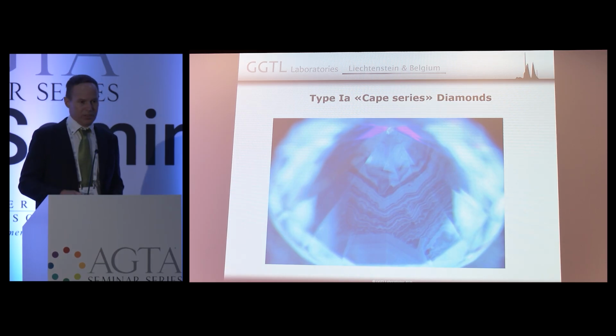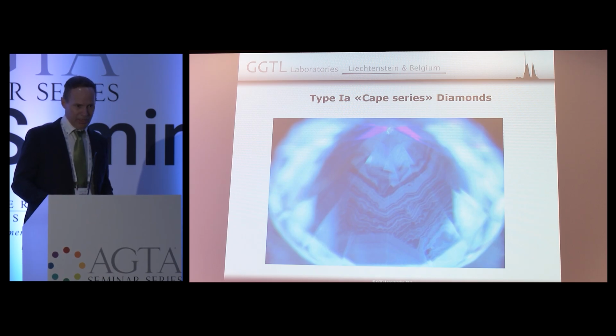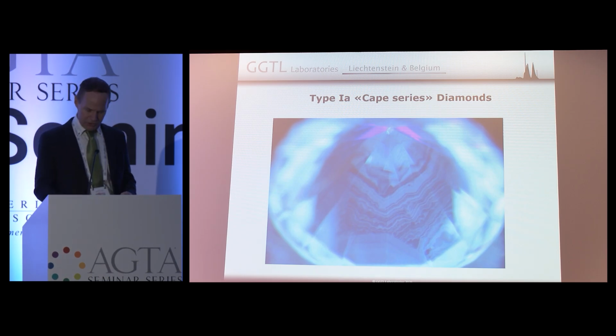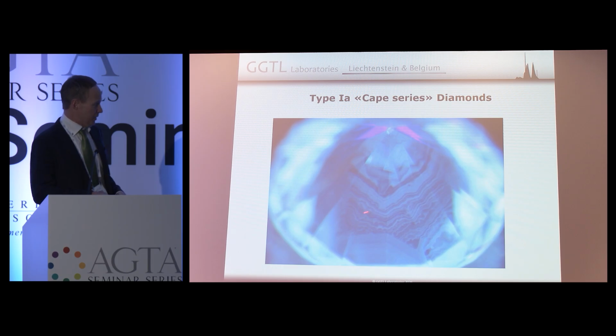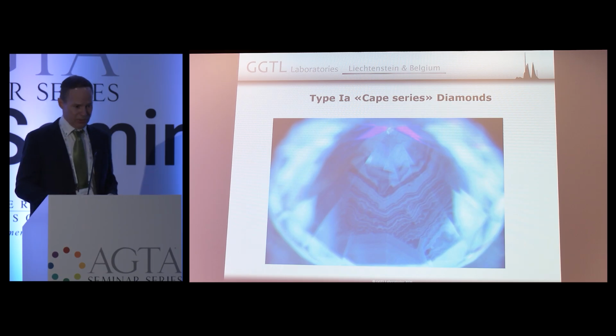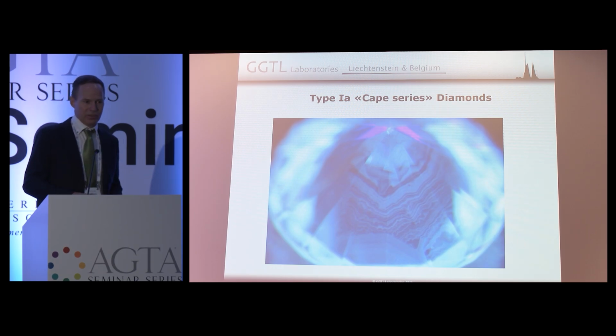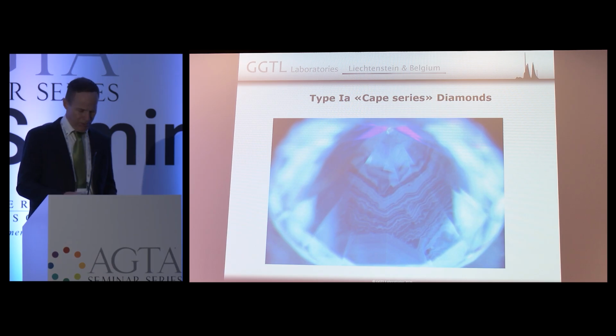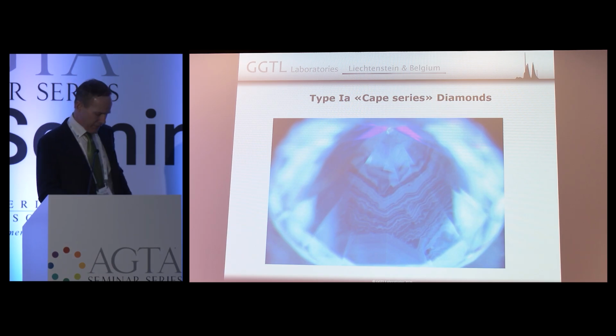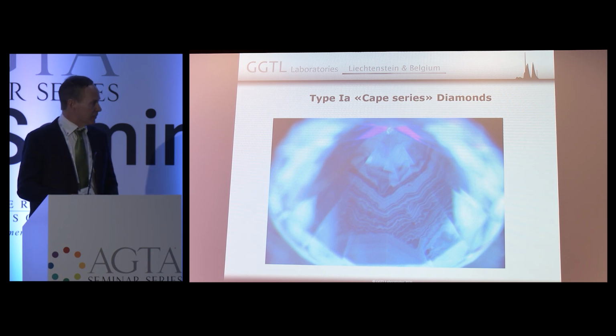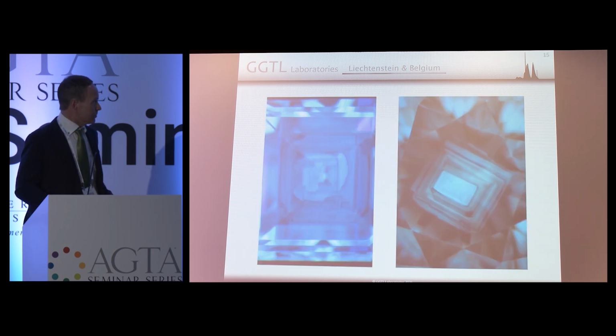You often see some small sectors that are of cuboid growth. It's much more common in vivid yellow type 1B material. There you see lots of cuboid growth. And you can visualize it with deep UV excitation really only. If you look at this stone on the long wave, it's just going to be plain blue, so it won't be very, very interesting to see. This gives you much more insight into the growth of the diamond.